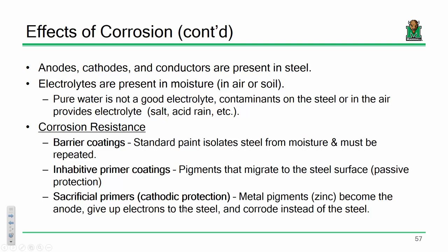But if you've got salt in that water, if there's acid rain going on, I'm talking about environmental effects on our infrastructure. Usually it's not just water, especially around here. So for instance, it's the winter. What do we put on our bridge decks in the winter? We put road salts, right? Those chlorides penetrate into the deck, they hit the rebar, bam. What happens to metal when it rusts? It expands. So what do you think happens to a bridge deck if you've got rebar cast inside it and that rebar is beginning to corrode? It expands and it cracks. So there begins issues of maintenance in our industry.